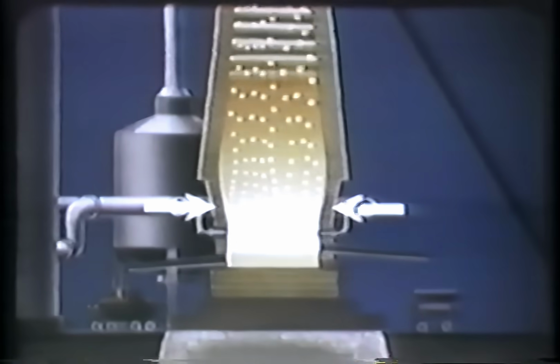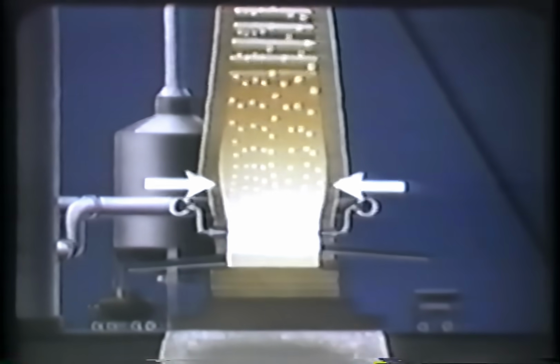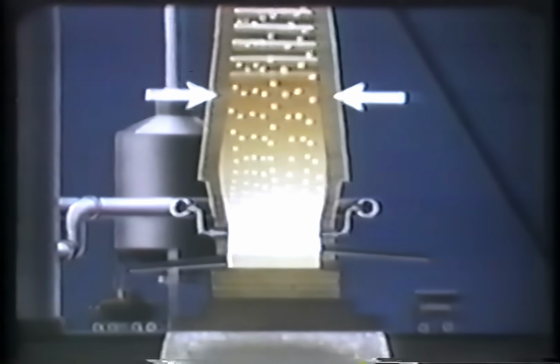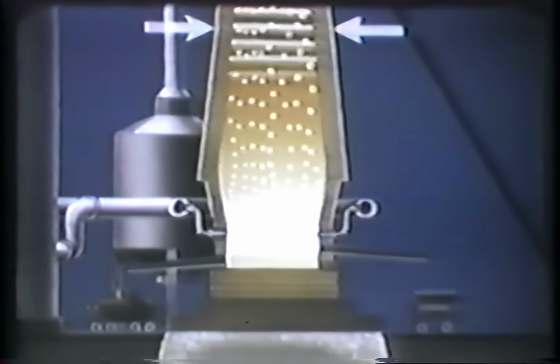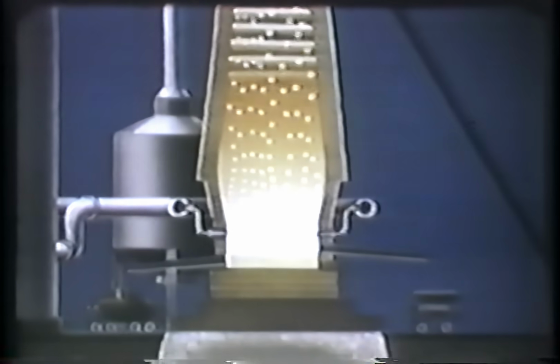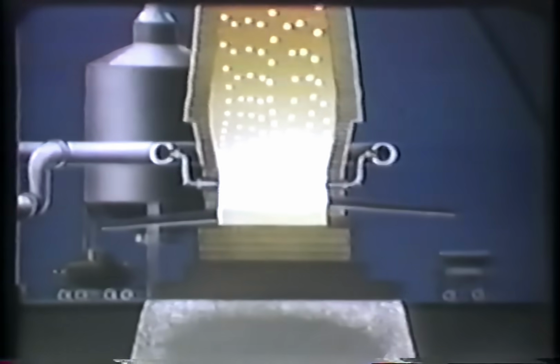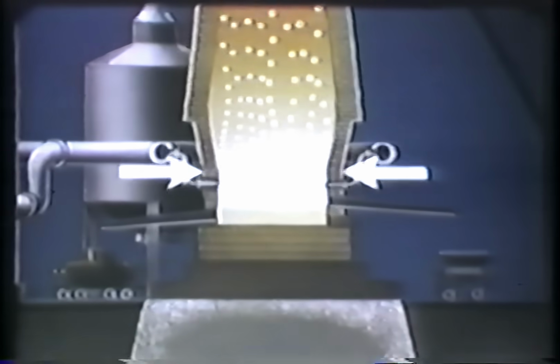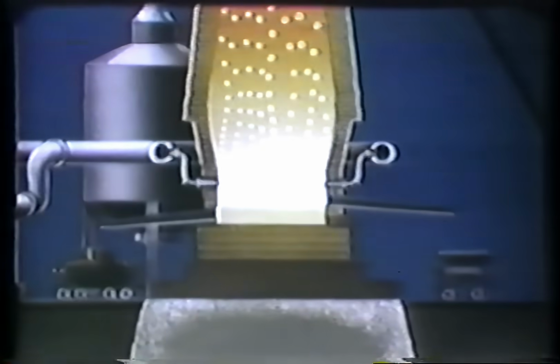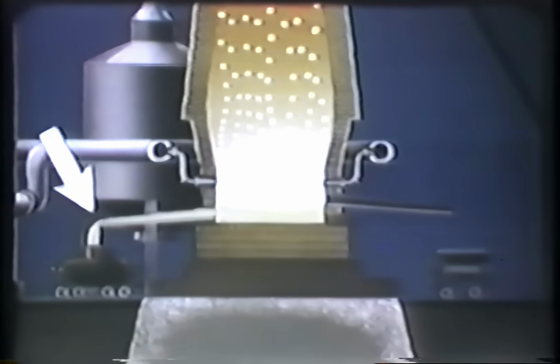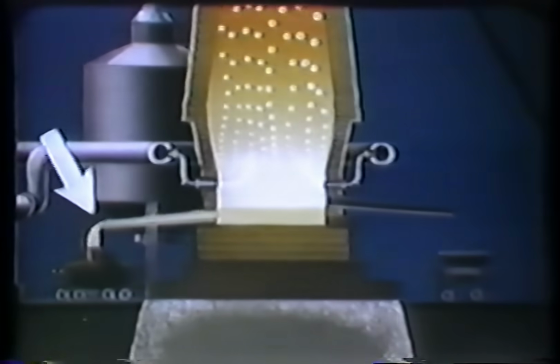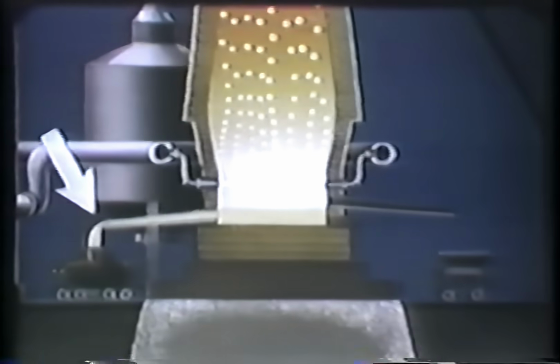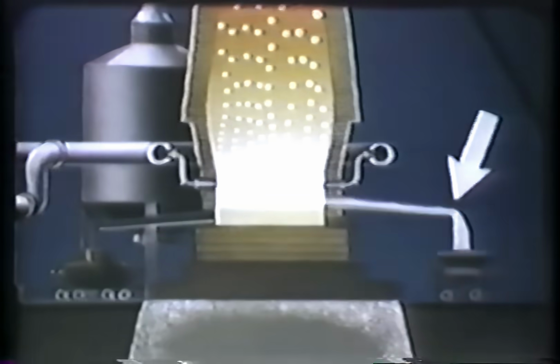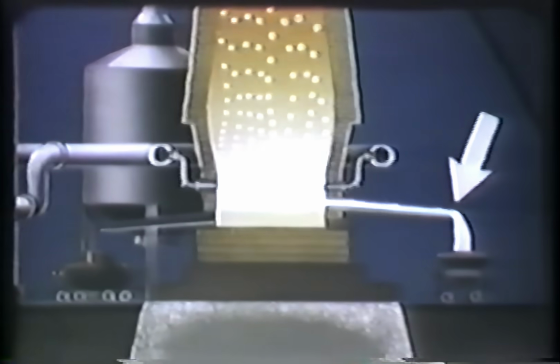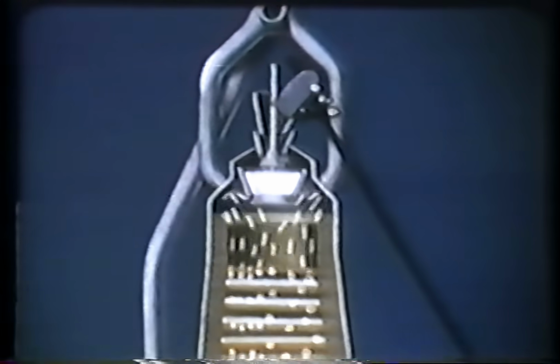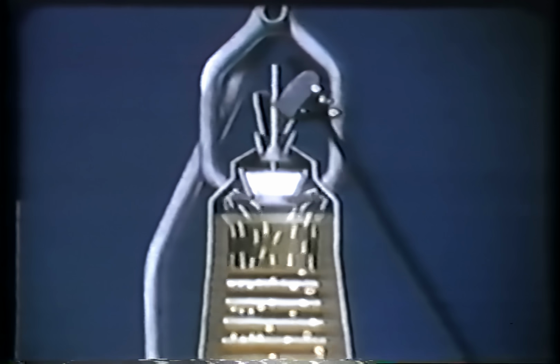Inside the furnace itself, preheated blasts of air burn the coke in the lower section. Heat and gases from the coke rise through the furnace and reduce the iron oxide pellets to iron, which then melts. As the liquid iron builds up in the hearth at the bottom of the furnace, it is periodically cast and taken to the steelmaking furnace. Impurities from the ore, ash from the coke, and fluxes melt and are removed as slag. All the while, the process of adding raw materials at the top of the furnace continues.